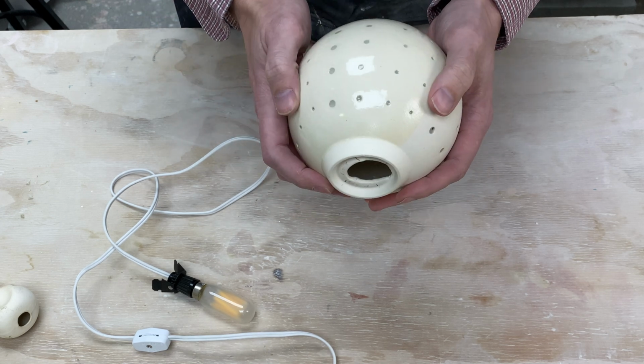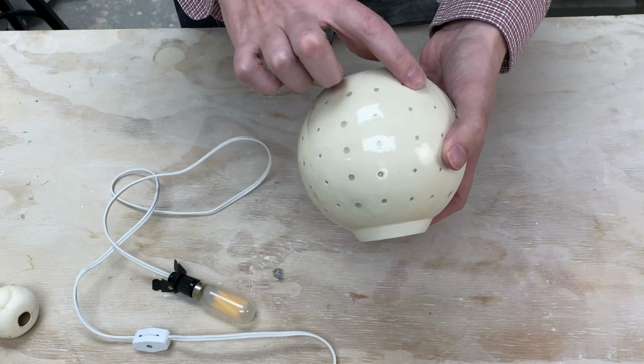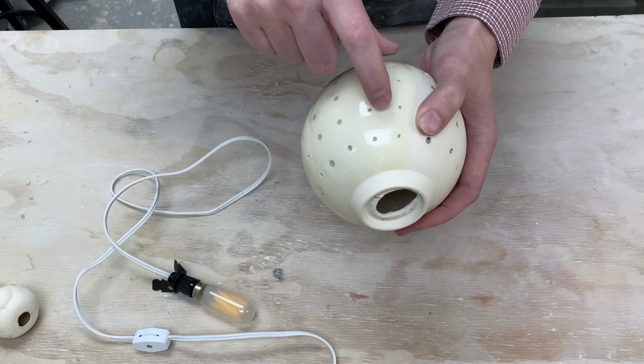And then finally, the digital fire glaze. Again, this worked really well. I don't see any pinholes. Where it spilled over on top, I don't notice anything at all. And the bottom seems okay. This one here is recessed a little bit, but it's still completely covered. So that's great. There definitely is a difference in these 2 glazes, and I was curious about that, and we see it here in the pot. The digital fire glaze is able to span those holes better than the first fire glaze.